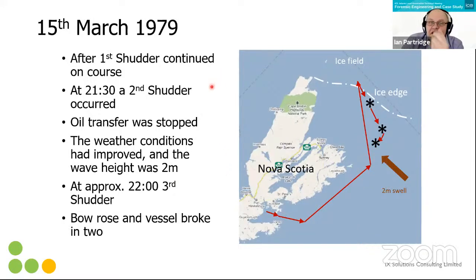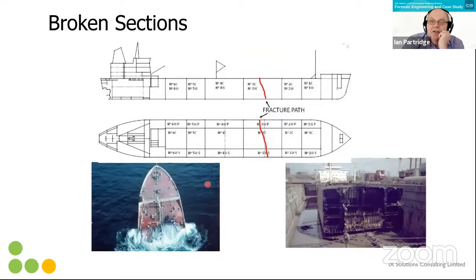A second shudder occurred at 9:30 at night. The oil transfer was stopped. The weather conditions were better, so there were only 2 meter swells in wave height now. Finally, around 10 o'clock that evening, there was a third shudder. The bow rose and the vessel broke in 2. It snapped basically right along this point. These are the 2 parts, the bow and the aft. This is the aft when it was brought to port.